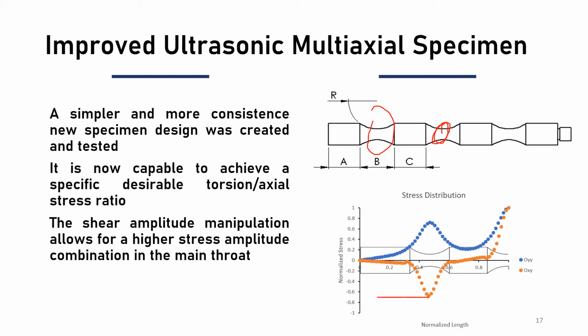Here we can see the result for one specimen where we clearly have a higher shear amplitude in the main throat and therefore a much higher stress combination in the main throat fatigue testing region. And this ability allows us to change to the desirable torsion axial stress ratio.